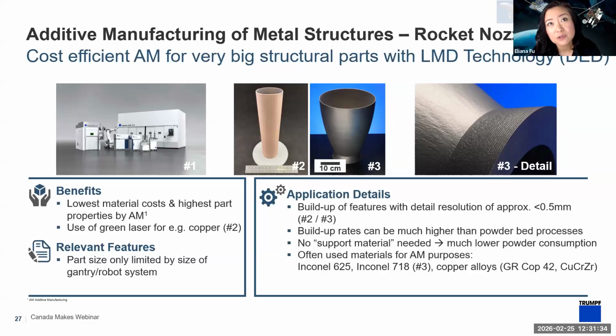Well, it's more difficult to do that with laser powder bed fusion, but you can do it with LMD because of some of those restrictions. You're not constrained by the build envelope of a powder bed chamber, but you just use blown powder to put the material where you want it. So this actually has the lowest material costs and the highest part properties of any AM process.